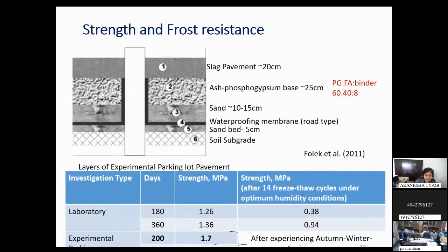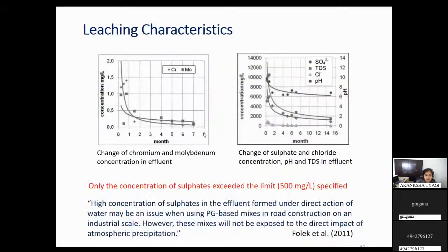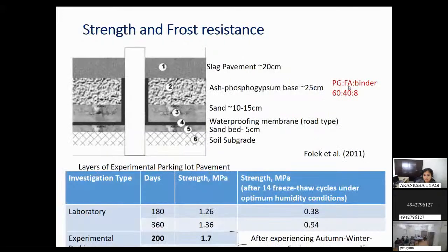So it was seen that in the field, this kind of material behaved quite better than in the laboratory test. Why? Because in the laboratory test, we are only testing this ash phosphogypsum binder. But above it, you can see that this is a combined system acting together. That is why field studies are important, because the field performance may be different from the laboratory performance. And in fact, they also studied the leaching characteristics of this phosphogypsum fly ash binder, this type of mixture.